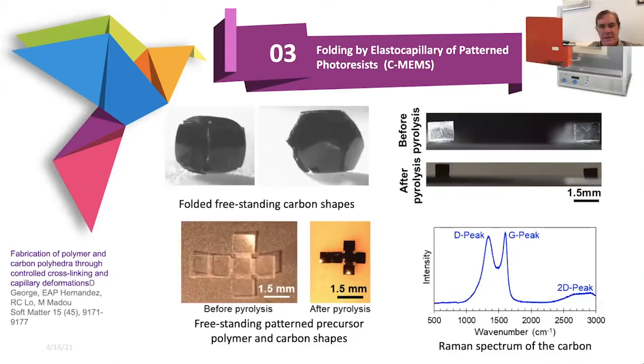So let's show that. This is the shape, in this case going to a cube. And this is the same shape after pyrolysis. And these are the shapes in carbon. You can build pretty much any platonic solid you want. Over here, you again see the polymer shape and then the shrunken carbon shape. If you look into the carbon material here, the microstructure in this case is very glassy-like, as you can see from the Raman spectrum, with prominent D and G peaks about equal in strength, indicating a glassy carbon microstructure in here.